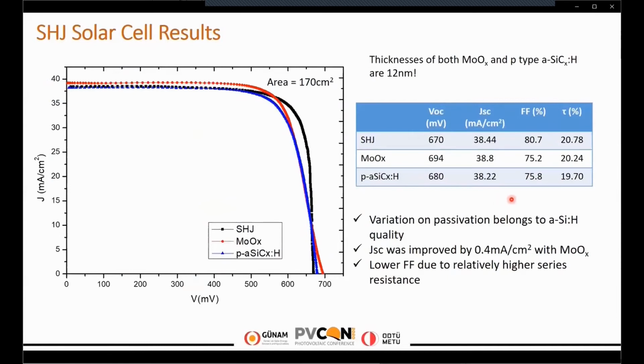For the standard silicon heterojunction solar cell, we have achieved 20.78% efficiency with a relatively high fill factor value. For the structure with molybdenum oxide, we have achieved 20.2% efficiency, but mainly we have faced a series resistance problem on that structure. Due to the series resistance, fill factor decreases to 75.2%. For the p-amorphous silicon carbide, we have achieved 19.7% efficiency. The important point about molybdenum oxide is that we were able to improve JSC by 0.4 milliampere per centimeter square.